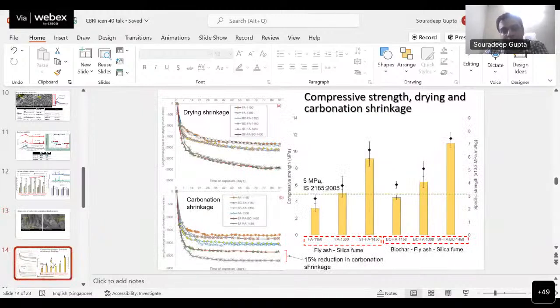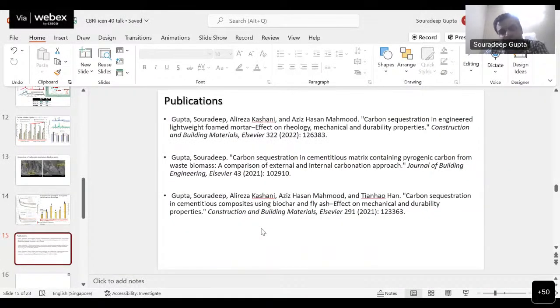We also have to take into account the standards, or the recommended strength, that we need to achieve after carbonation. Very comfortably, we can achieve a strength of 5 megapascal and above, up to about 10 to 12 megapascal, after carbonation of biochar mixes, which satisfies the recommendation as per Indian Standard 2185. We have also seen that after carbonation, the shrinkage of biochar admixed mortar has reduced by about 15% compared to the control mortar, which is good because there is less likelihood of cracking and other durability problems with reduction in shrinkage. A few publications have come up, and this was partly a project funded by the Australian Research Council, and part of the work was done at IAC using the startup grant that I received. You can refer to these publications for further details.